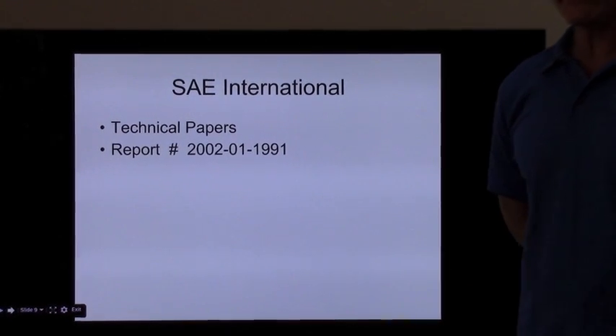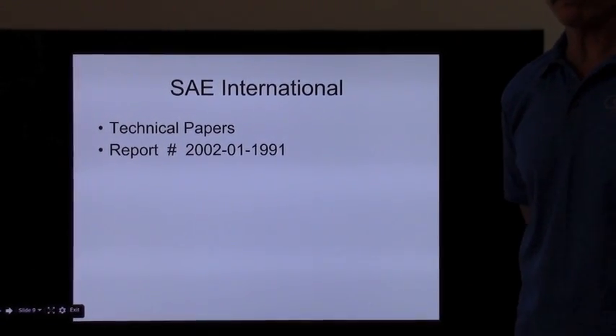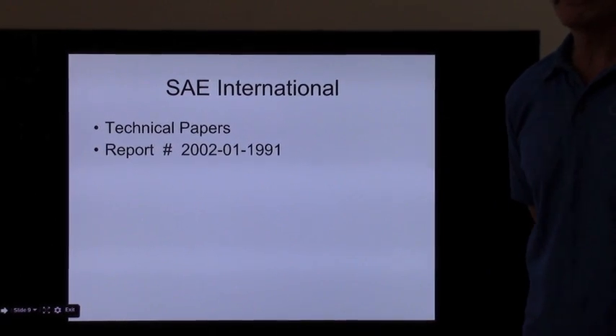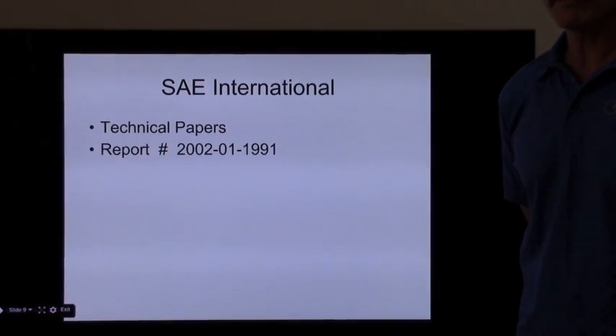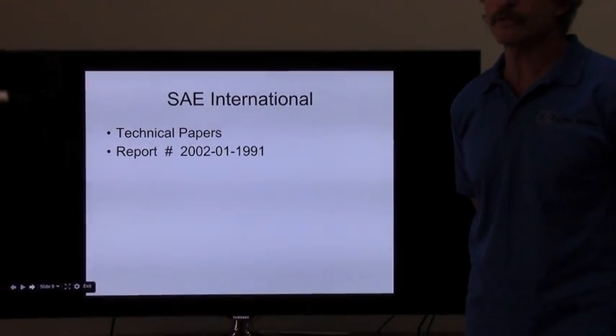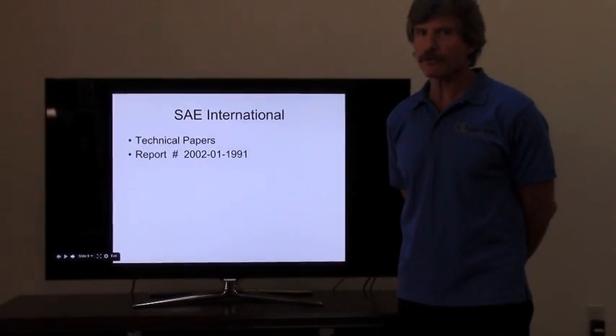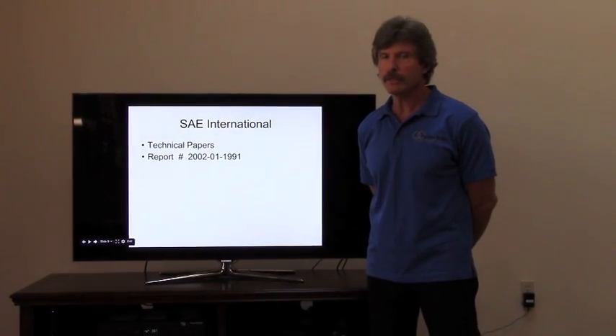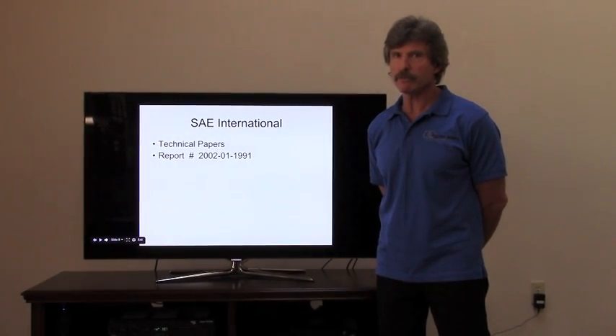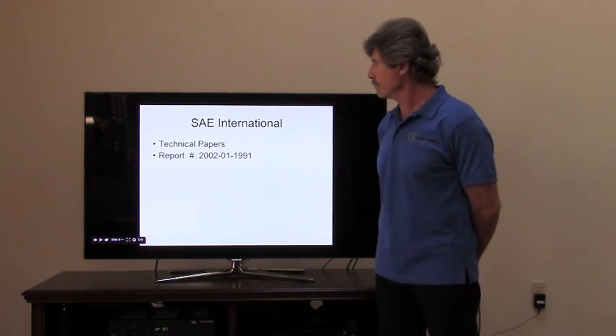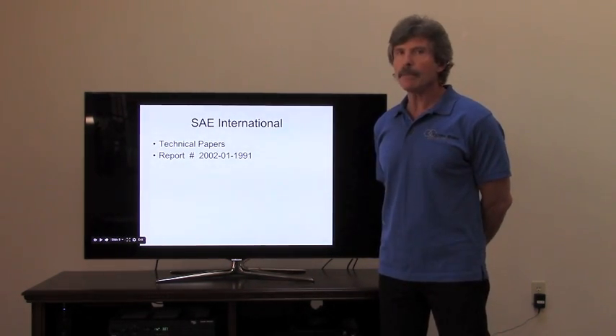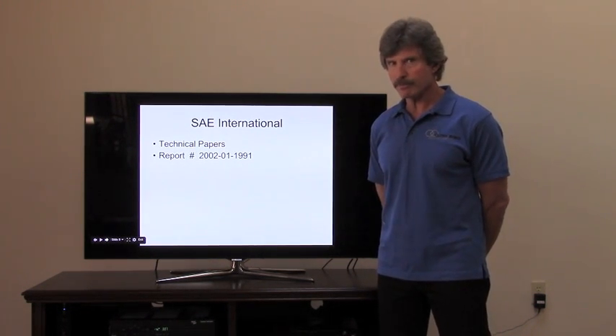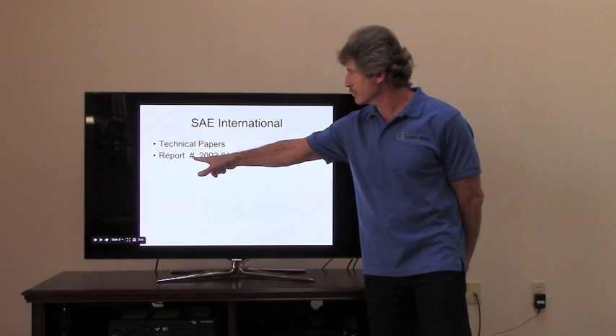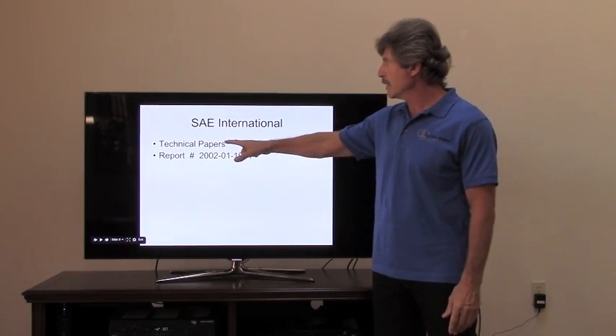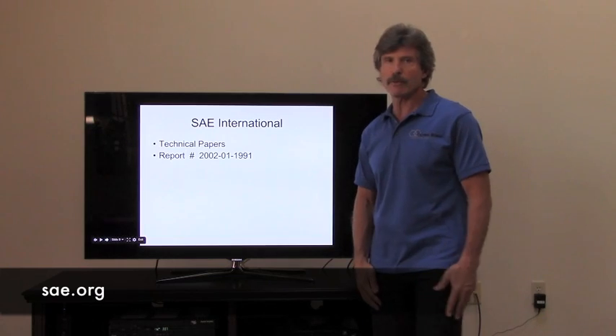SAE, Society of Automotive Engineers. We did some testing of windshields back in 2002. And believe it or not, you can't find too much testing done on windshields. And this was a fracture test. So we were doing a test just to confirm that the edge of the windshield fractures easier than the middle. It was done by Knott Lab, and the Society of Automotive Engineers published this report. You can buy this report, that's the report number, for about $10, $11 on the Society of Automotive Engineers website.